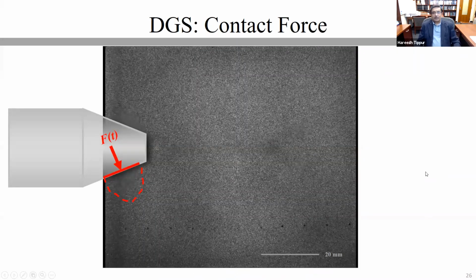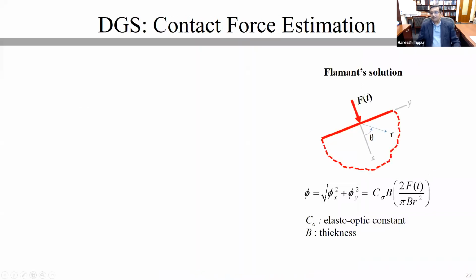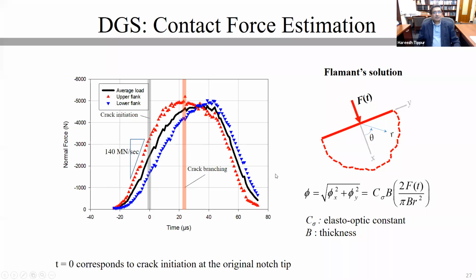Of course, like in the case of photoelasticity, you can also do contact stress analysis. You can use the same approximation of the Flamant solution and back out your force history by simply measuring the resultant angular deflections of light rays. So this is the history that we were able to capture. Of course, this was a completely different experiment. The loading history was not necessarily all that symmetric as in the photoelasticity experiment, but nevertheless you see the behavior of this trapezium-shaped loading history that is typical of these types of Kolsky-bar experiments.